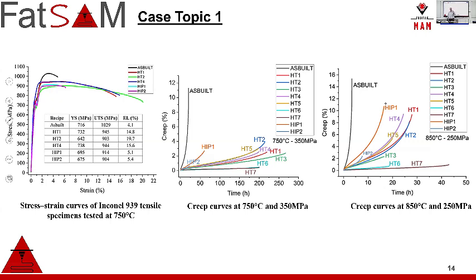In the creep mechanism, there are three stages. The primary creep stage, which is parabolic. The second is steady state, and the third is, like fatigue, a rupture area. In the third stage, unexpected rupture mechanisms occur. But in the case of HT7, it is less than 1%, even after 40 hours at 850 degrees Celsius, which is not applied for these materials at these temperatures, and 250 megapascal.